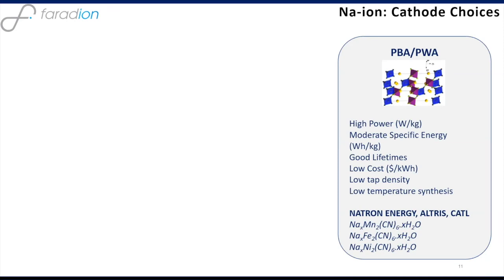Altris in Sweden. And now a new entrant in the last couple of years has been CATL, who are apparently looking at developing a sodium ion cell chemistry based on Prussian blue analog materials. The problem with these for an energy application is that these materials generally have a pretty low tap density. So they've got good power, they've got good lifetimes. If they're based on iron or manganese, they have low cost, but the low tap density and the low true density of these materials generally makes them unsuitable for making high areal capacity electrodes. So I think they're better suited to power applications, not so suited to high energy applications.